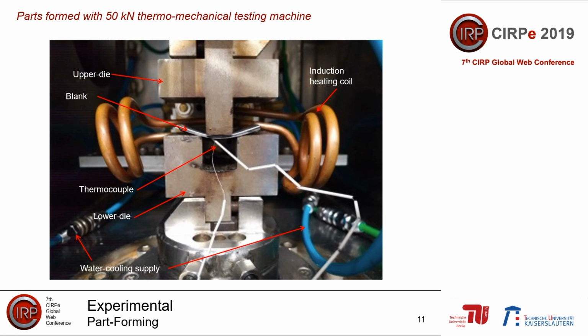So this is our setup for forming. This is our upper die, our lower die, induction heating coil. This is our water cooling supply for water cooling of the die. Then we have our sample, our thermocouple spot welded to the lower surface of the lower dummy metallic sheet for temperature control.